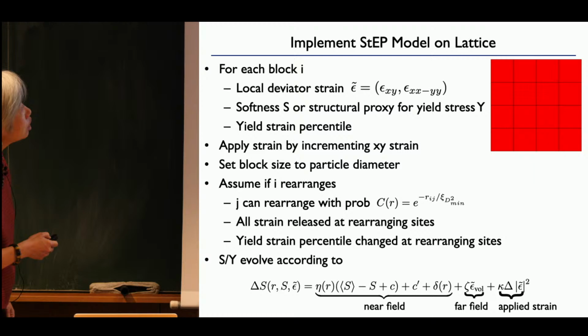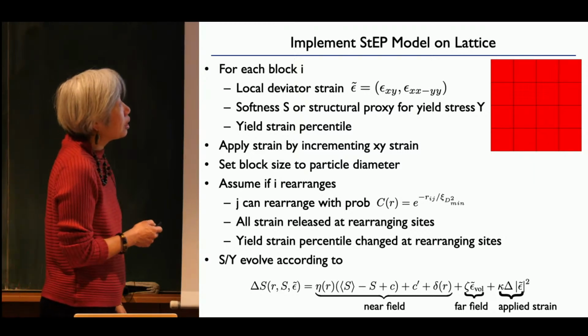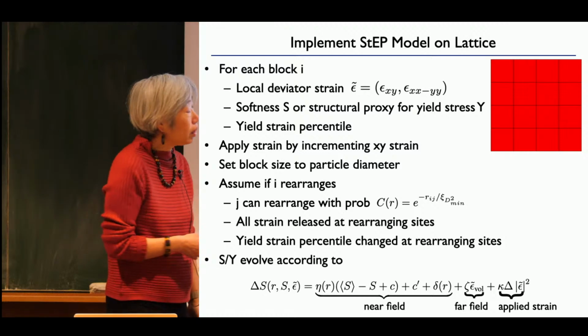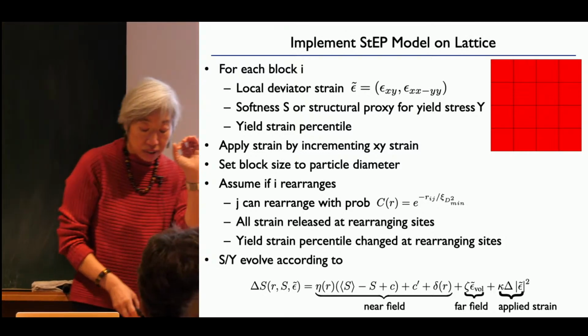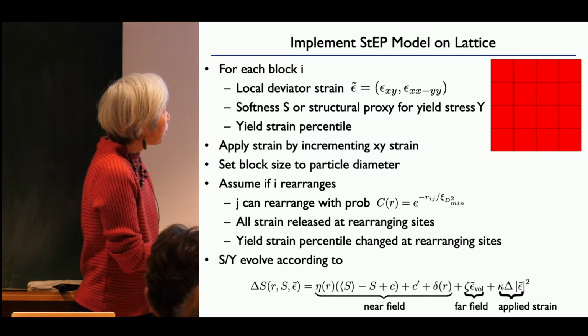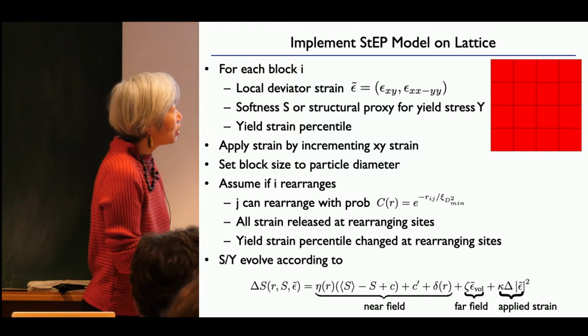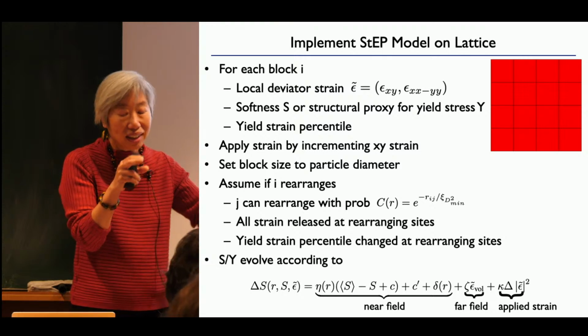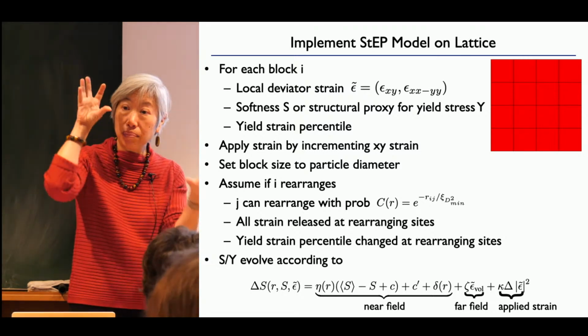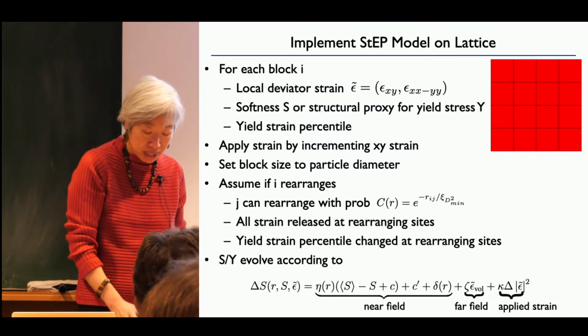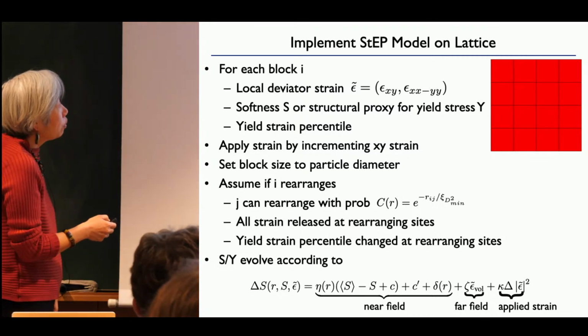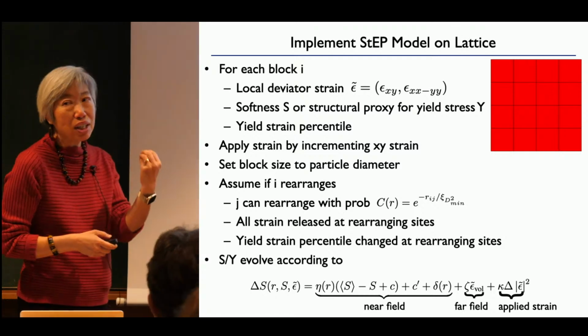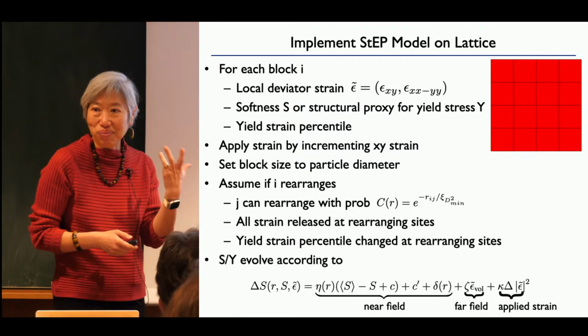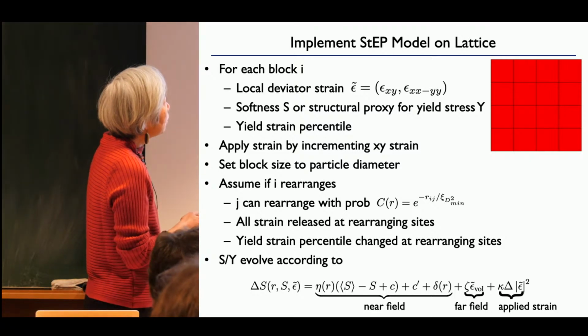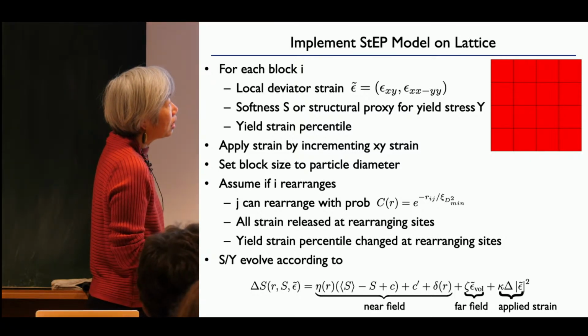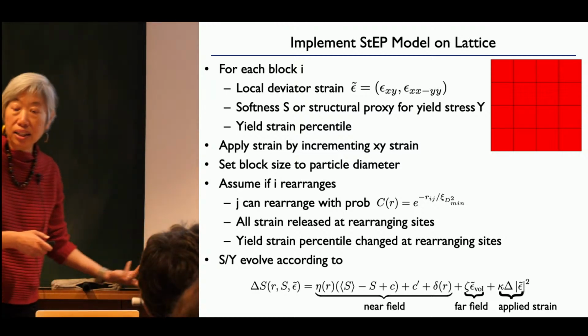All right. So now what do we do? We're going to just set the block size to the particle diameter. But we have seen that when we look at delta squared min, there's a correlation length. If we look at correlations of delta squared min, as you saw, they were correlated in space. That takes into account that a rearrangement does not involve just one particle. So when this rearranges, neighbor blocks can also rearrange, but with this length scale. That's the size of the rearrangement.